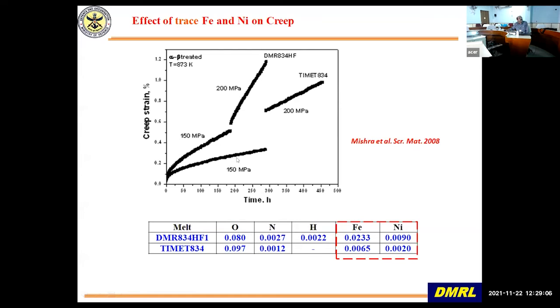And you can see this is the imported IMI 834, which has a lower amount of iron and nickel. As compared to that, this has a higher amount of iron and nickel. And you can see, at the same stress level and temperature, there is a jump in creep strain. That is, it is deteriorating as far as creep resistance is concerned. This also jumps up, so you are having much higher creep strains. So you have to be very careful about iron and nickel in high temperature titanium alloys.